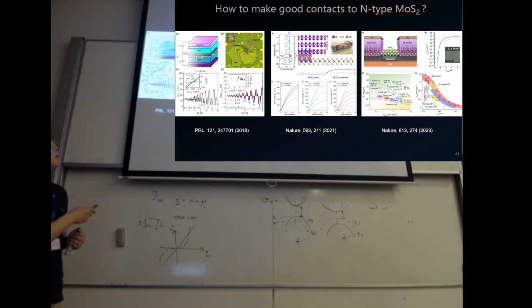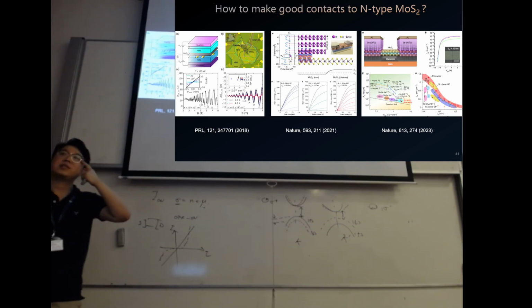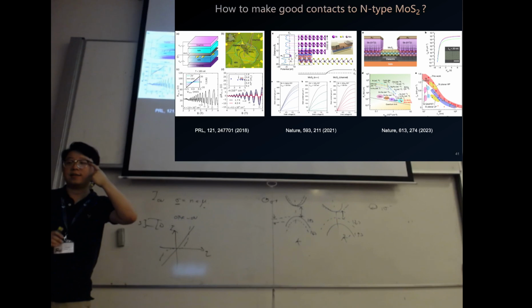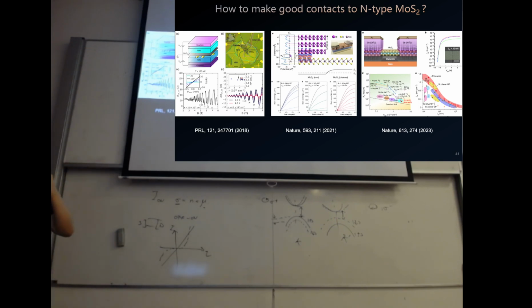And what they obtain is very good performance of IV curves. Unfortunately, in their paper, they just investigated the system down to 70 Kelvin, so they didn't measure anything below. We don't know why, but at least this is a good sign. Bismuth can be a good contact.